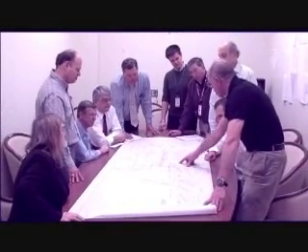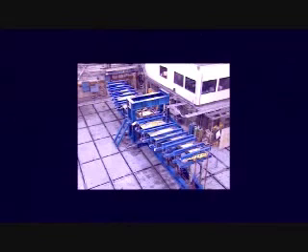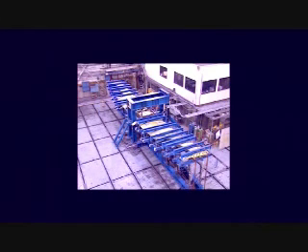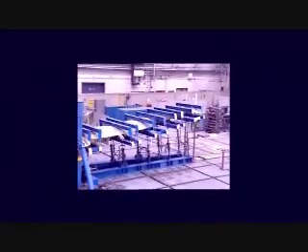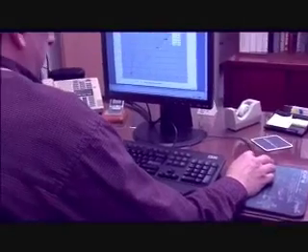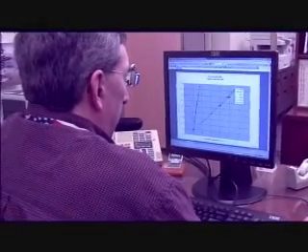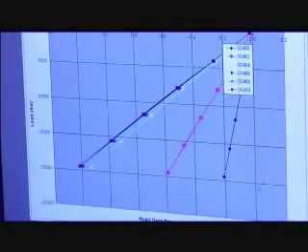integrity and mission availability. Fatigue testing of the wing was performed in 2003-2004 to identify areas requiring reinforcement and to validate crack prediction methods and inspection requirements. The wing was placed in a fixture and loaded, using hydraulic jacks to replicate the spectrum of stresses representative of the A-10 aircraft maneuvers in the post-Desert Storm timeframe, 1992 to 1999. Load cycles were applied, representing equivalent flight hours of severe usage. Marker band loads were also applied for the purpose of identifying the point in time at which damage occurs.